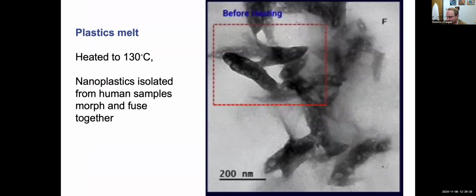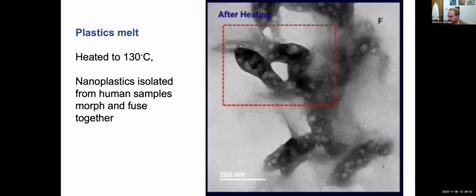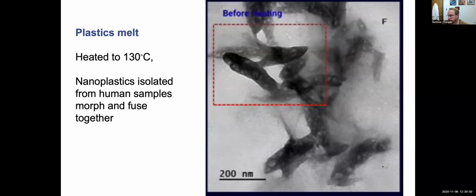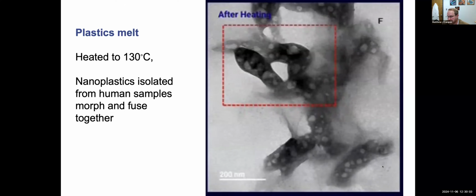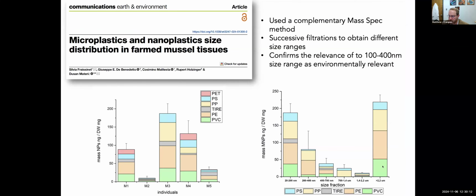This is one of the things I think is the coolest characterization of these nanoparticles we've done, and that's simply to take the TEM grid and heat it to 130 degrees, which is the melting point for polyethylene. You can see before heating and after heating, these flakes start to deform and fuse together. So there really is melting going on at this temperature, which is about as important a confirmation as we have that these really are plastics derived from the human tissues.